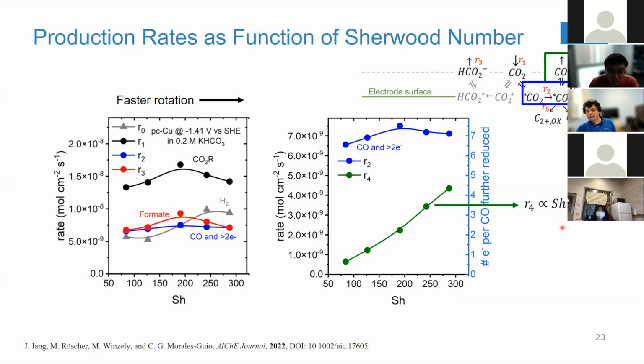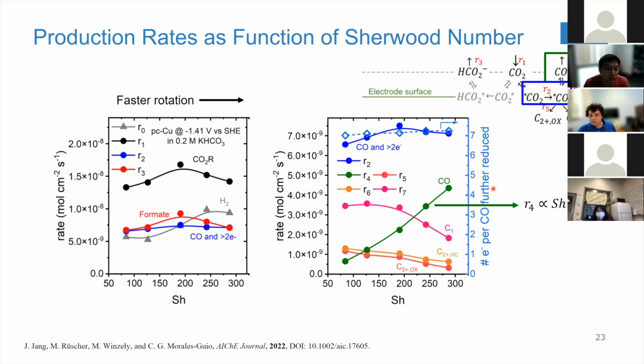And what we find is that the flux of R4 is actually proportional to the Sherwood number, which should not be surprising. The transport of these molecules is a first order process. As we systematically change the mass transfer properties, as we change the Sherwood number, we expect a linear correlation with that CO local concentration. And if you look at the different products, methane, hydrocarbons, oxygenates, these actually decrease. The assumption in the current literature is that if you increase the mass transport, you lower the local pH, and so you should increase the production of methane. But what we see is that that's not the case. Even though the pH is lower as we improve the mass transport, ethylene and methane both decrease in production rate.